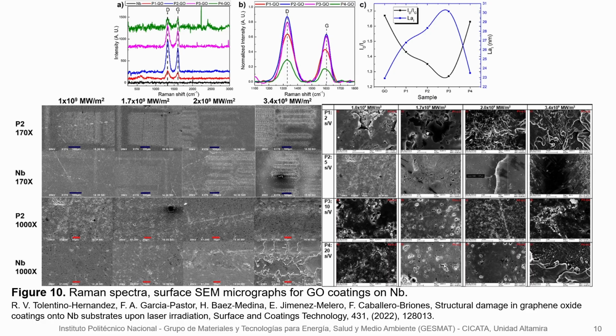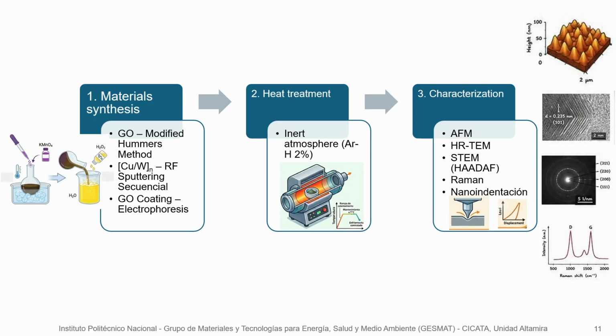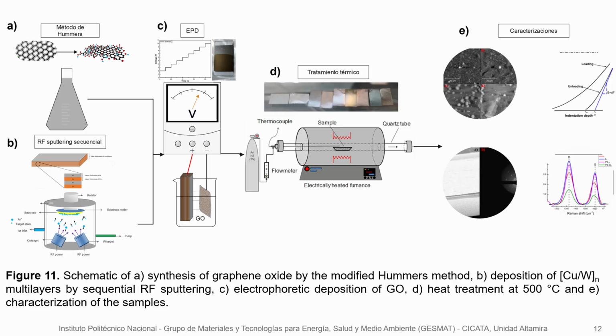This work was divided into three sections. First, the material synthesis. Second, heat treatment. And third, the characterization of the samples. Briefly, we synthesized graphene oxide powders by the modified Hummers method. Then the multilayers that we synthesized were made by sequential RF sputtering.